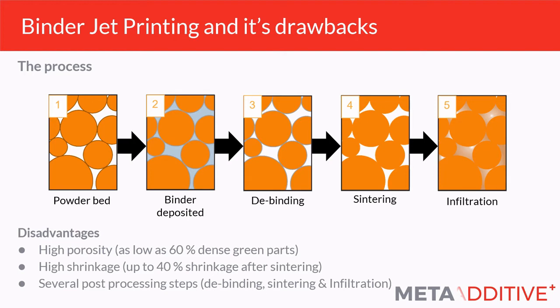But because we've bound it with a polymer, and we don't want polymers in our metal components, we need to debind. And that debind step can be quite lengthy, anything from 15 hours to a week sometimes, depending on the process and depending on the component. And that debind step often leaves carbon residue behind in your component, which is detrimental to the overall component and limits the applications it can be used in. It's also a lengthy step, but also if your part is too large, you can't get enough binder out. So it limits the size as well as the complexity of the geometry that you can print.